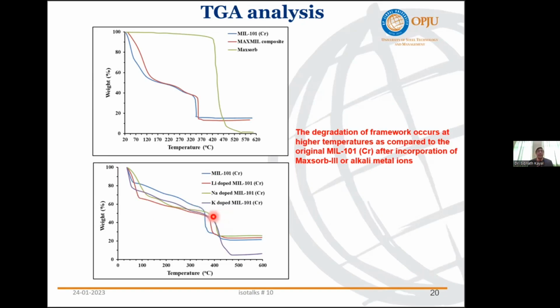And after 350, you can see there is a sudden weight loss. This sudden weight loss is due to the complete degradation or complete collapse of the MOF structure. So after this temperature, the MOF structure completely collapses, and that means after that, this structure is no more your MOF. That is called the degradation temperature. Above this degradation temperature, the material will collapse, and before this temperature, the material can withstand up to this temperature.